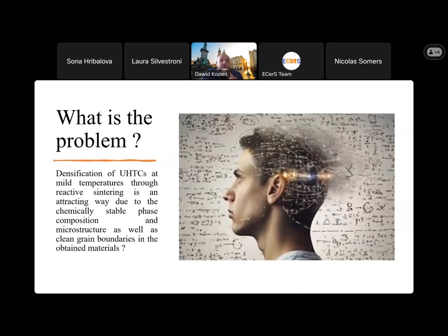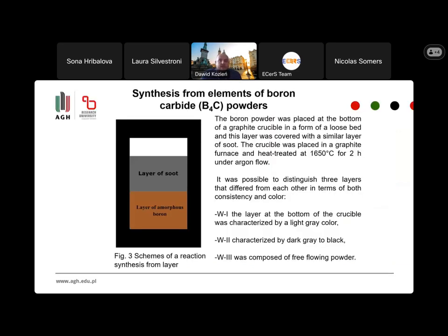Everybody can ask, what is the problem? The problem is densification, and mild temperature reactive sintering is attractive due to chemical stable phase composition and microstructure as well as clean grain boundaries in the obtained material. So I started that during my PhD. I started working on synthesized nanopowders of boron carbide that could be used as a raw material in sintering. And we prepared, and now have a European patent on, how to prepare very fine grains of boron carbide.